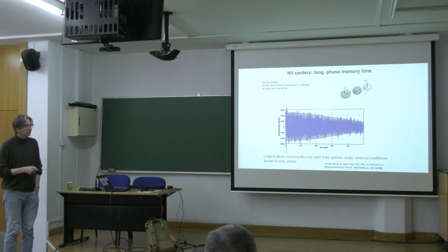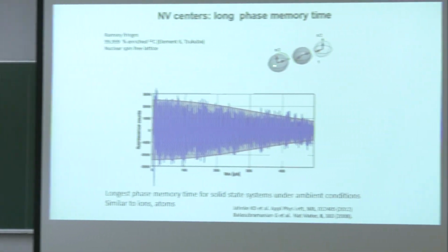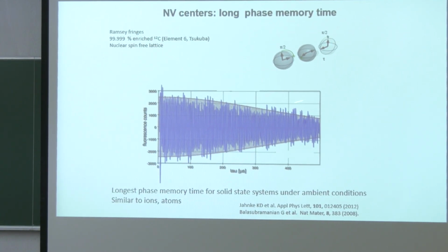Actually, here is an example of this experiment. I excite a coherent state of the NV center, a superposition of 0 and 1, and leave it to precess under ambient conditions. And I measure this precession by interrupting it and measuring the state again at the end. And you see that this precession lives for a few hundreds of microseconds. So a few hundreds of microseconds of T2 time is an important resource, especially if you think about ambient condition applications. Not many qubits, and I would say no other qubit, can have this long coherence time if you're talking about electron spins. Nuclear spins can have longer coherence time under ambient conditions, but for electron spin qubits, this is the record value.